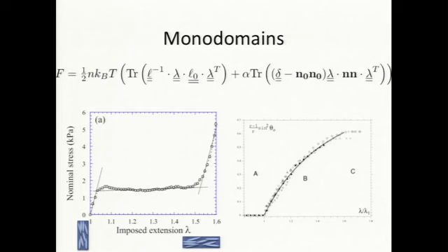So I would say one final point about this. There is a very good energy to describe this. This is originally in microscopic configurations, although I would think about this phenomenologically. But basically this is the old part of the energy, the part with the complete soft mode, plus alpha times a term which has some n naught in it, which is an imprinted preferred direction. So this part is completely soft. This part, proportional to alpha, which we expect to be a small number, gives you a weak preference to line up your director along n naught.